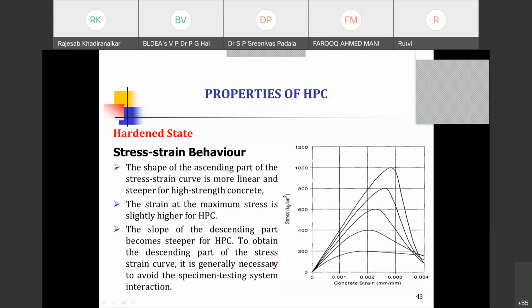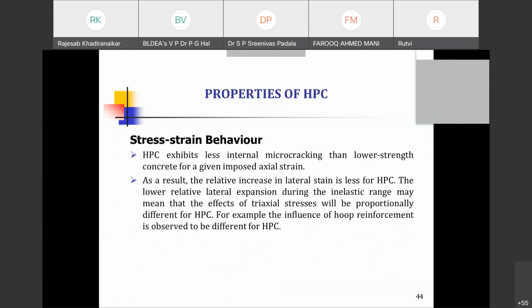To obtain a descending part of the stress strain curve, it's generally necessary to avoid the specimen testing system interaction, what we call the platen effect. Also, you should go for closed loop systems rather than stress control. You have to go for strain control, then you'll be able to capture this behavior particularly. So HPC exhibits this increase in the linear stress level, and then you'll also find a very interesting observation,